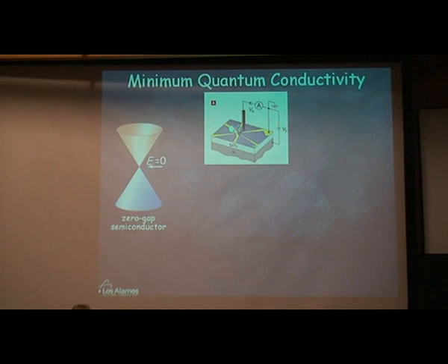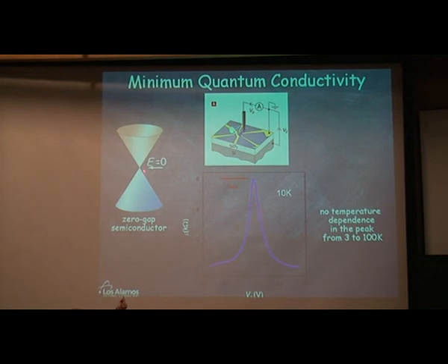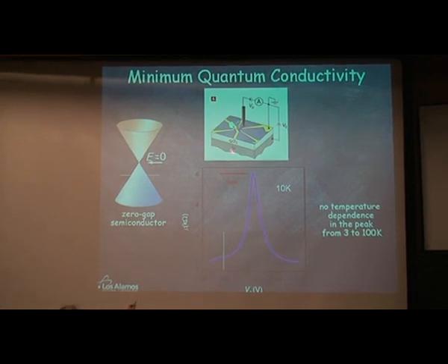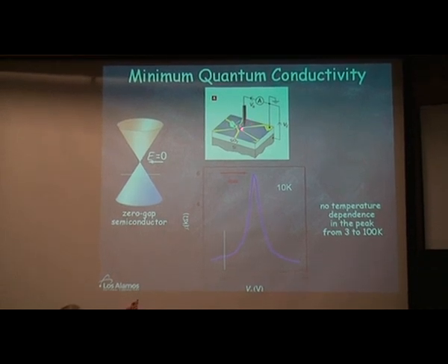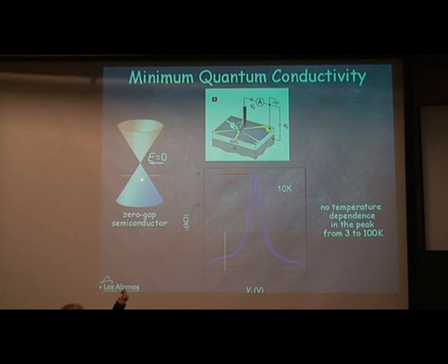Now, what one can do is produce a field effect on this material by doing the back gate and changing the filling factor. Let me call this point the Dirac point. You can then bias the back gate properly. So this is a flake, and suppose you have some electronic contacts coming to this flake. You can bias it so the chemical potential will be below the Dirac point, at the Dirac point, and above the Dirac point. And you can clearly see as you sweep this bias, you hit a maximum in the resistivity, which is consistent with barely conducting, very few carriers available for transport in this material. So this is a measure of the Dirac point, how narrow this peak is. People do make quite a bit of issue about the exact value of this conductivity.